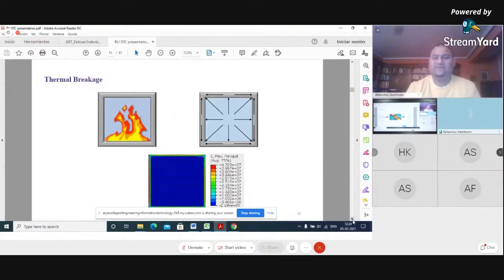So again, one more experiment and numerical model that we have produced. You can see that there are two cases. In the first case, on the left-hand side, expansion is allowed, and on the other side, no expansion is allowed for the glass because of the frame. If we have a frame, what will happen during fire? During fire, the temperature of the glass will increase, and it will try to expand. Once it tries to expand, there will be stresses, and those stresses will cause a stress gradient throughout, and the glass will break.